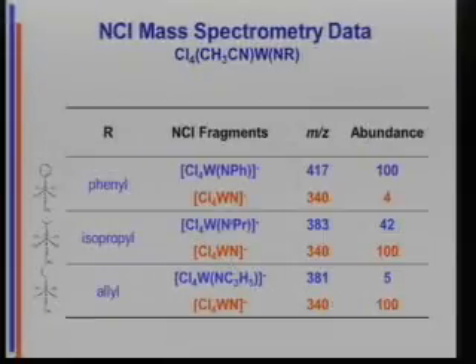Now we could actually probe the ability to break the CN bond, here's our original molecule, by mass spec. Now, if you're going to tell me that mass spec is gas phase ion chemistry and my CVD process is neutrals, I know that. But it turns out that this actually works better than we deserve, and that the weak points for scission of the molecule are pretty much the same as the ones in the ion. So what I'm looking at here is I'm changing the R group on the nitrogen, that mini nitrogen you can barely see, from phenyl to isopropyl to allyl. So what I'm doing, physical organic chemists, is I'm varying the bond dissociation energy of that CN bond.